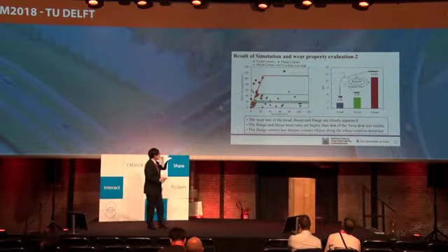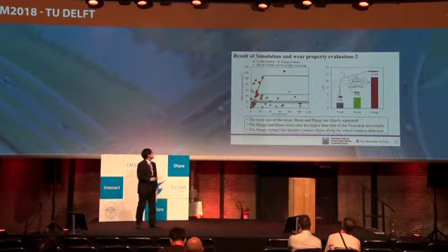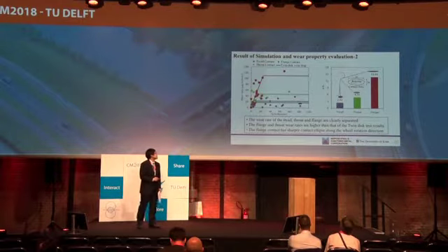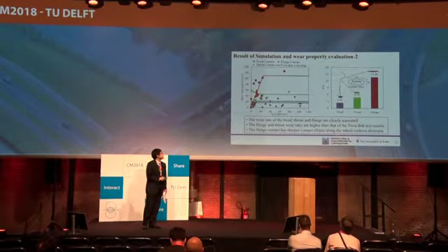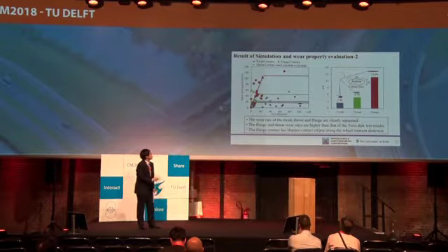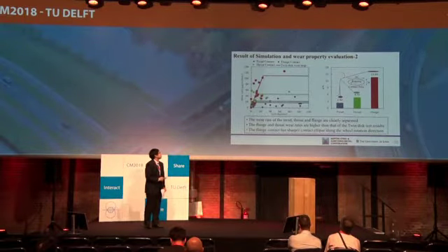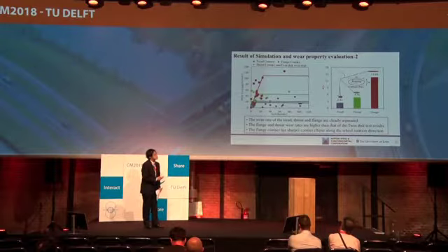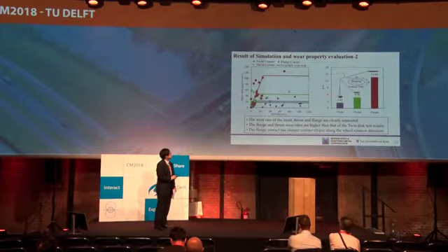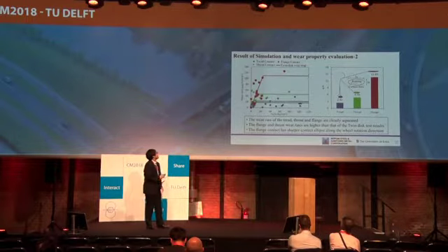This figure shows the aspect ratio of Hertzian contact areas for tread, throat, and flange. From this figure, the flange contact is sharply elliptical along the wheel rotation direction. This aspect ratio of the Hertzian contact area is strongly related to the wear rate.